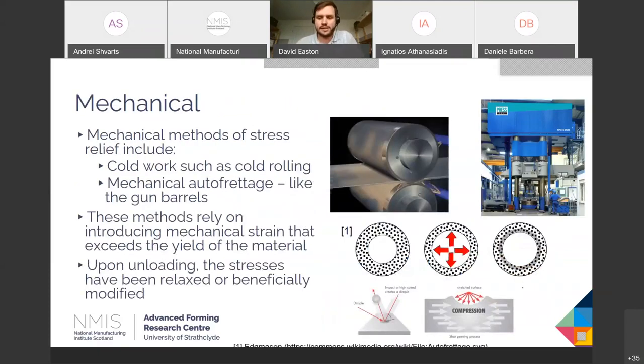Mechanical methods. This is what I was talking about earlier with the gun barrel, where we apply a pressure in order to exceed the yield stress, we then remove the pressure and we get elastic recovery, which gives us the residual stresses that we want. And this is the same sort of fundamentals that we see in things like cold work and cold rolling. We're forcing material to move beyond its yield point, and then when we remove that external force, whether it's pressure or a roller, the part relaxes and stresses are either relieved or opposite to what they were before.